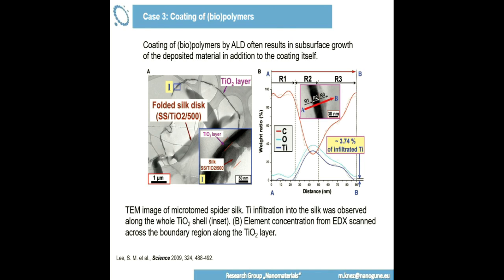You may have a coating on top of your polymer, so it's a cross-section of a silk. This is a coating around, but the problem is that below this surface you also have a deposition. It's inside of the polymer. So it's not on top, it's also inside. So both of them are happening at the same time. And this means that besides the diffusion on the surface and so on, you also have the possibility of an indiffusion of the polymers into the substrate, if the substrate allows it.